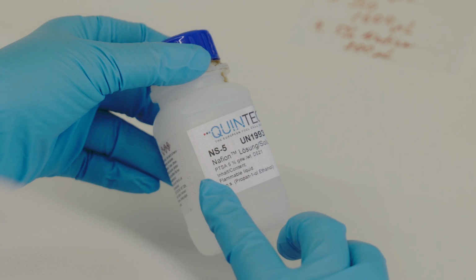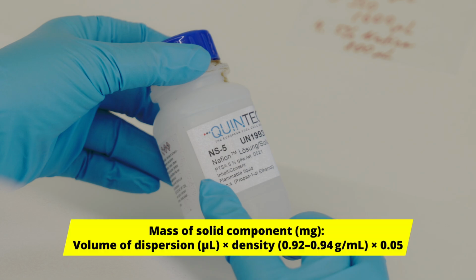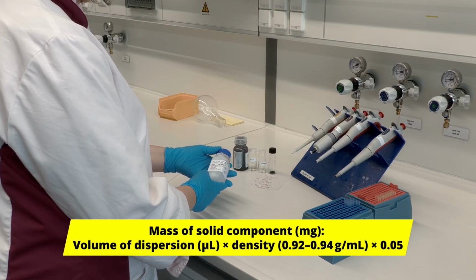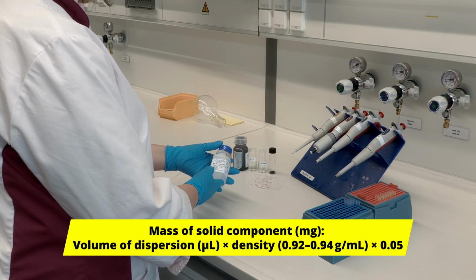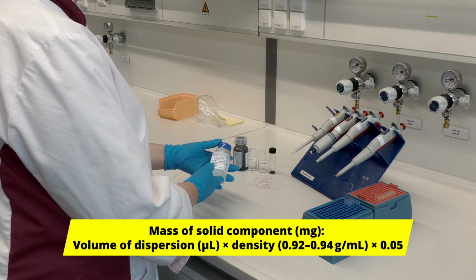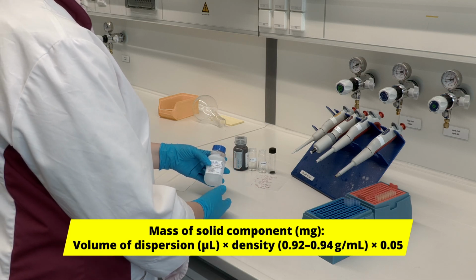And to calculate the mass of solid components, you have to use the next formula. Mass of solid component in milligrams equals volume of dispersion, in our case in microliters, multiplied by density, according to the data sheet 0.92 to 0.94 gram per milliliter, and multiplied by 5%.